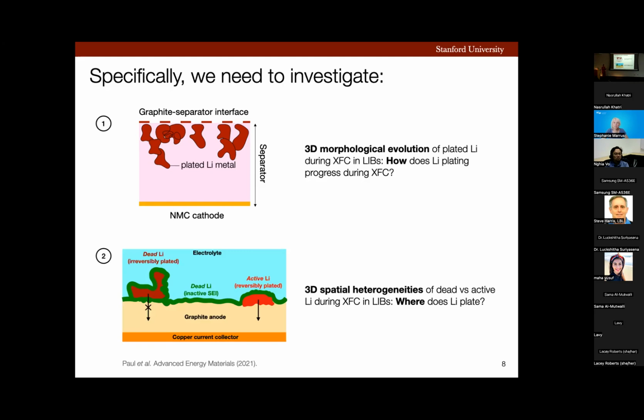In addition to understanding morphology, my thesis focused on understanding 3D spatial heterogeneities of dead versus active lithium during fast charging. Now, what is dead and what is active lithium? If you look at the schematic, you can see that we have active lithium, which is reversibly plated. This lithium has an electronic pathway open to it, which means it can accept an electron, intercalate into the graphite, and find a pathway back to the NMC cathode during the battery discharge process. Thus, this lithium does not cause capacity fade of the battery.